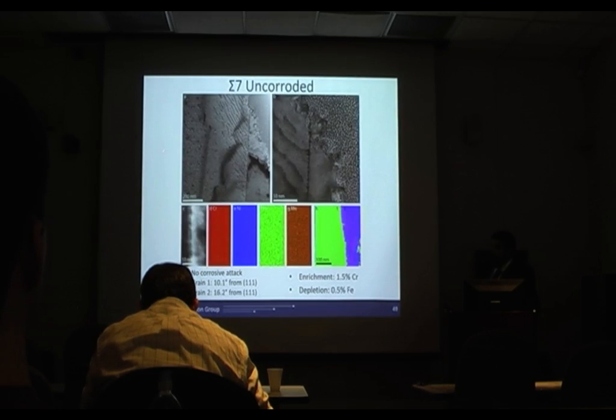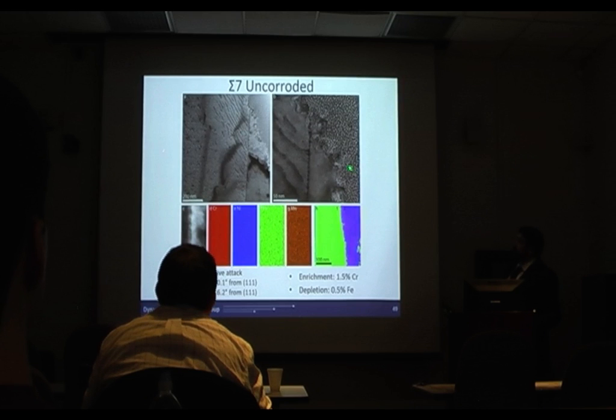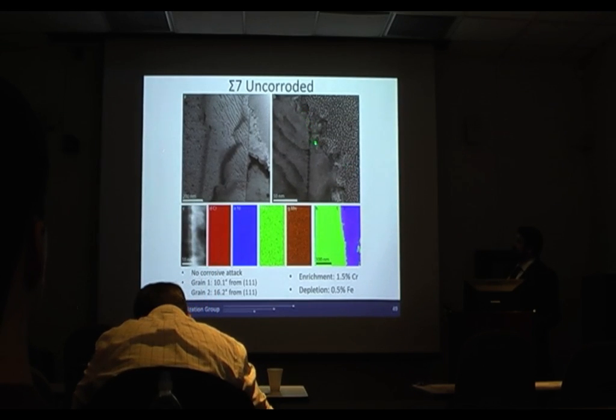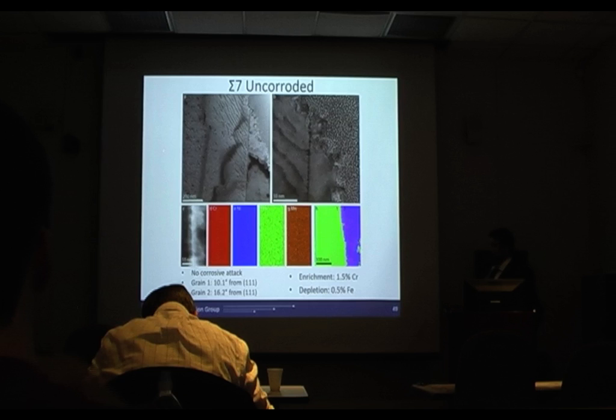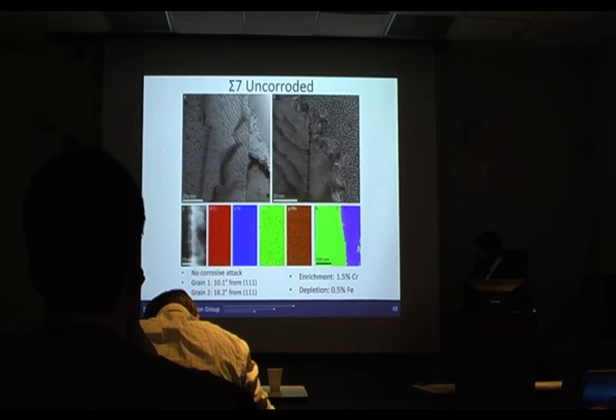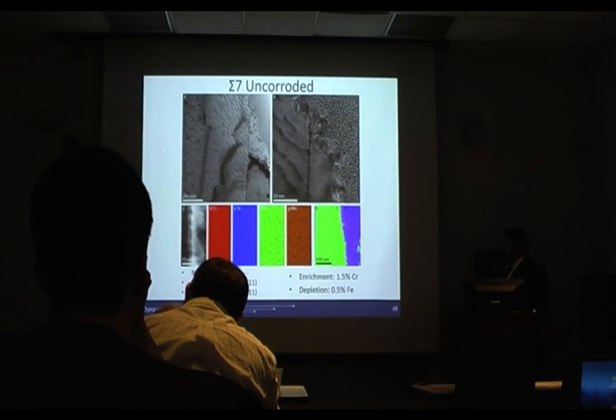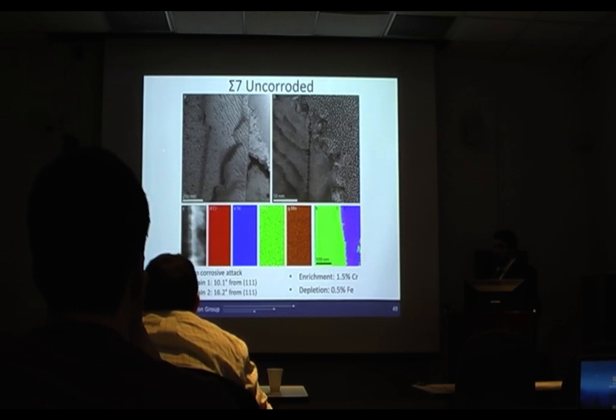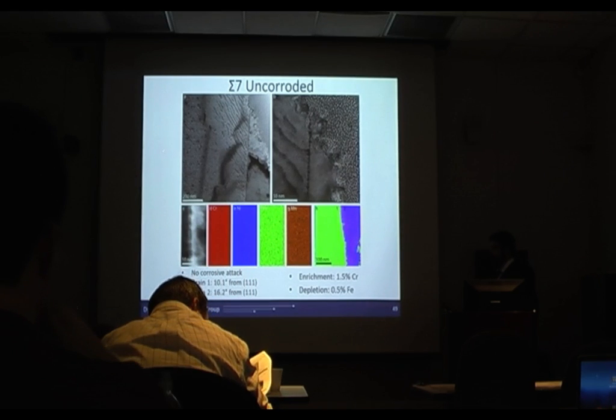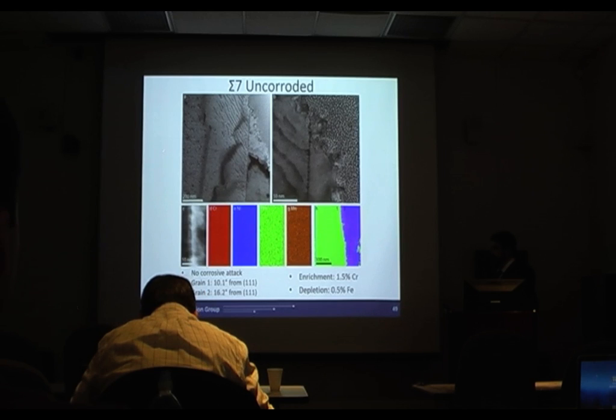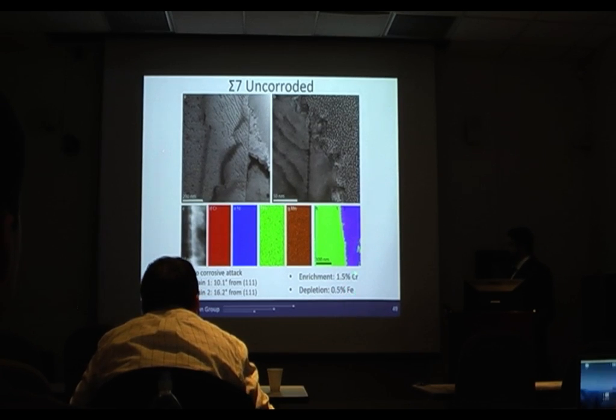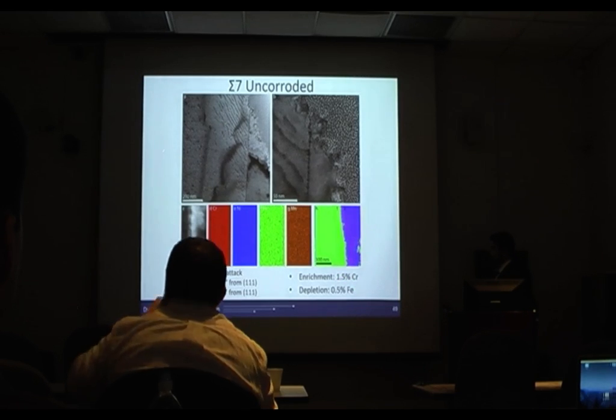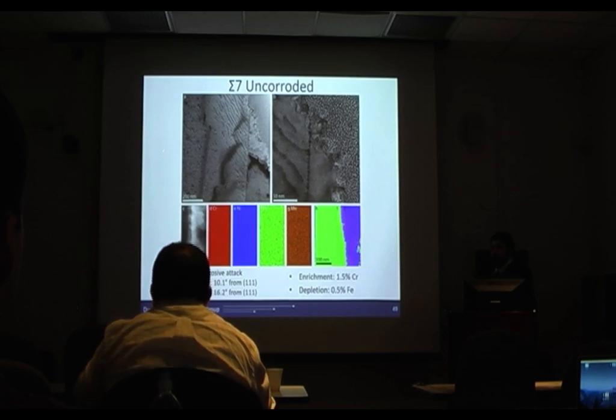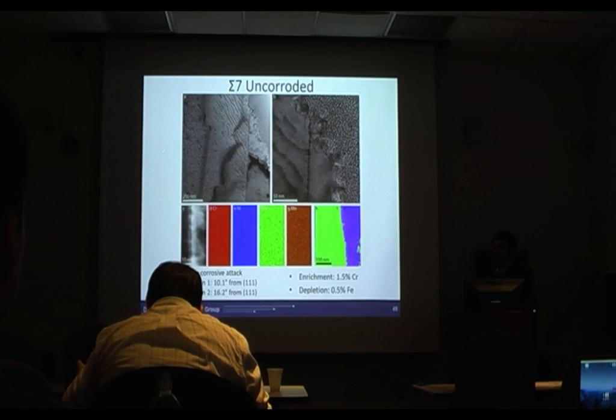And when we move on to the uncorroded one, you can see it's not attacked at all at that surface relative to the general surface attack. While it's closer to a 111, it's not actually terminating on it. It's about 10 to 15 degrees away, and we have slightly lower levels of chromium enrichment and iron depletion. However, that variation can also be caused by sample thickness and scattering in this technique.